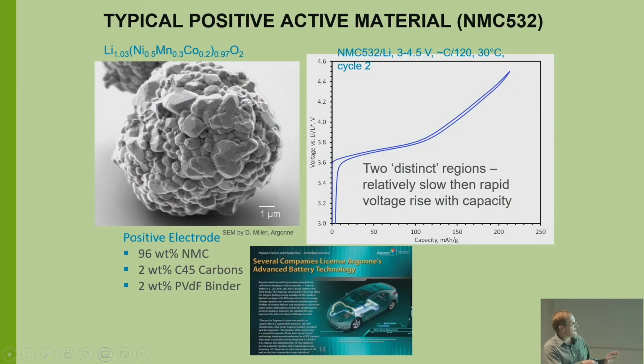Okay, so back to a little bit of science here. This is a nickel manganese cobalt oxide particle. It's NMC 532. There's primary particles connected with secondary particles. There's generally about 15 to 20 microns in diameter for the secondary particle. If we test this versus lithium metal, we get a voltage profile, and then we get our milliamp hours per gram. And as an engineer, those are numbers I need when I'm designing the electrode. I should point out, too, that Argonne developed the NMC material and has the patent on it, which was like 20 years ago, basically. So there's a lot of press releases on that. It was one of the big success stories in our department.